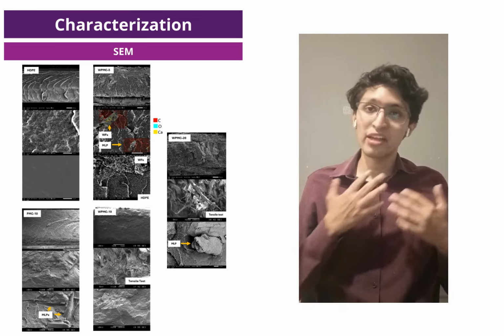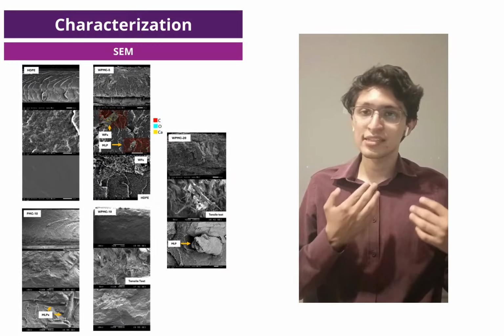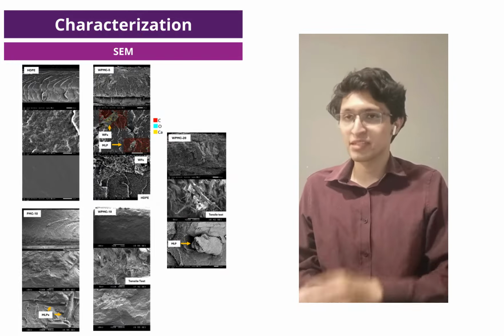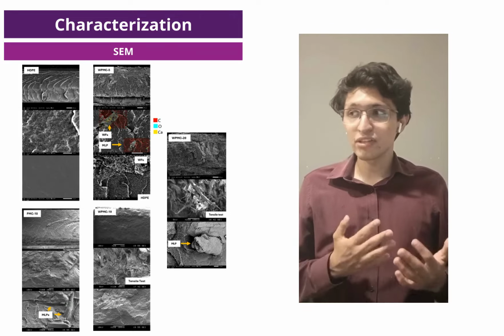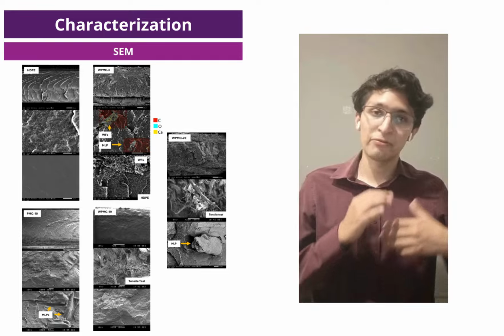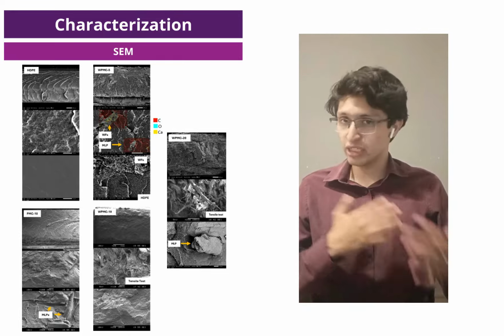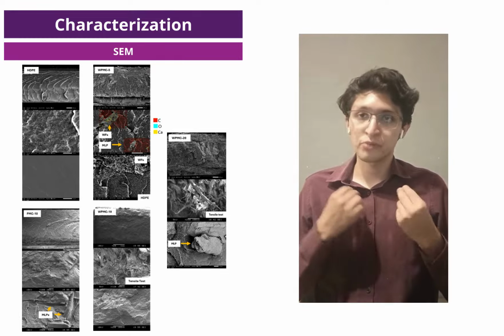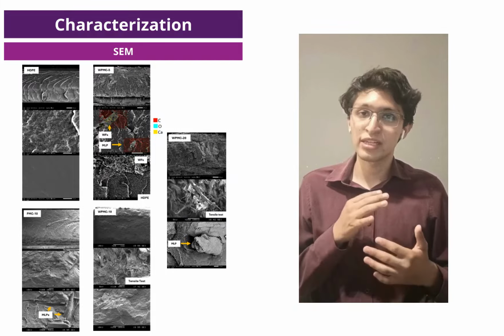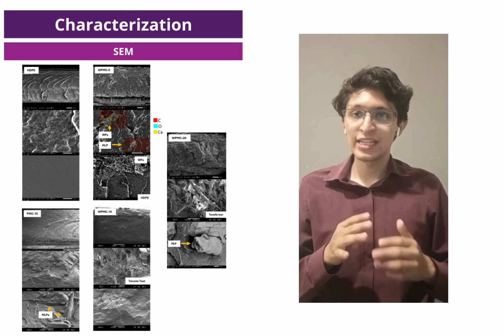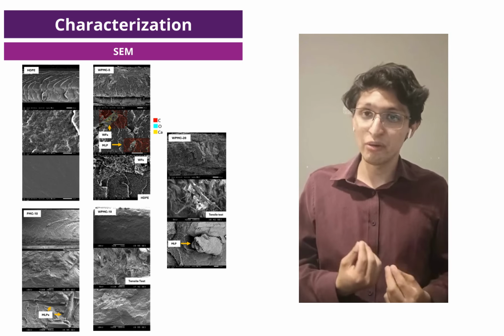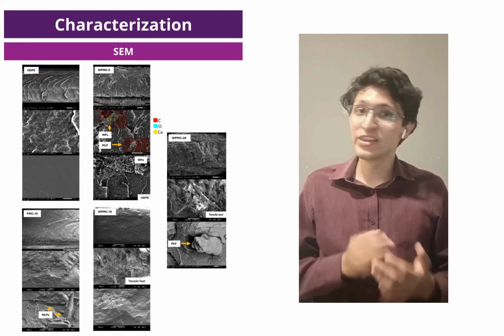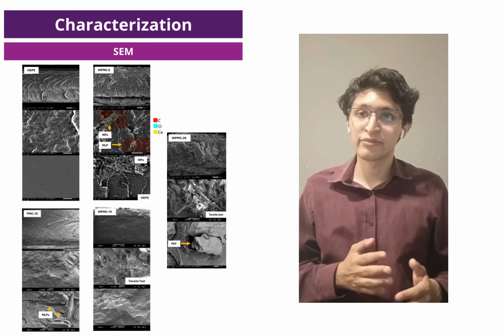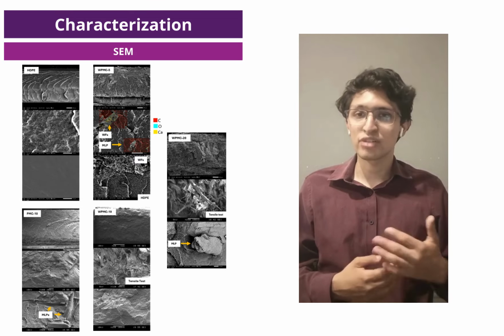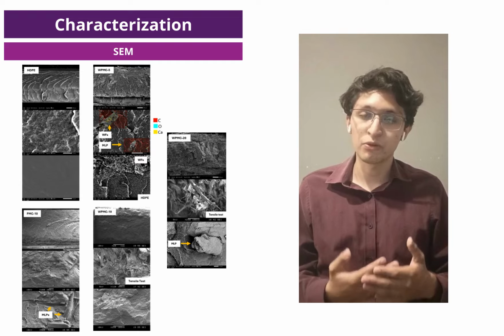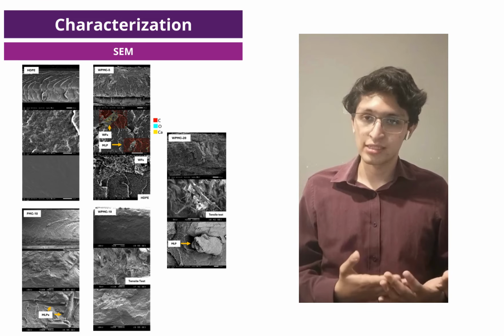Now let's pass on to the morphological analysis that was made through SEM on tensile test specimens and cryogenically fractured specimens. In my opinion, this is one of the most important ones, as it describes almost everything in the next slides. Let's start with the integration of wood. The integration of the wood fibers is almost perfect. There is a seamless transition between the polymeric matrix and the wood fibers, indicating that the treatment in fact worked very well. In contrast, the multilayer plastics did not have any integration at all, generating microcavities and inducing stress concentration points that are going to lower the mechanical properties of our composites.